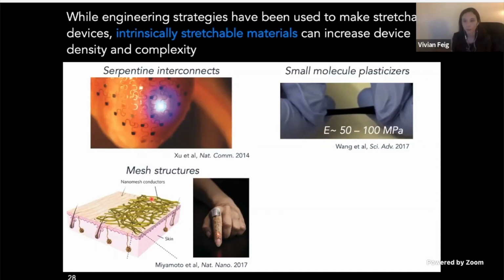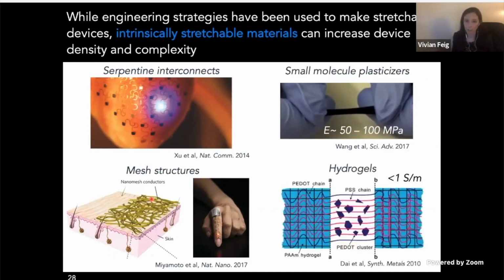And so going back to the first part of this talk, one of the really easy ways that we can make tissue level soft materials is with hydrogels. And indeed, there's been a lot of reported hydrogels that are highly stretchable and tough. At the same time, examples that have taken these stretchable gels and just blended in some conductive additive typically report low conductivity values of less than 1 Siemens per meter because they're not deliberately forming this conductive network.